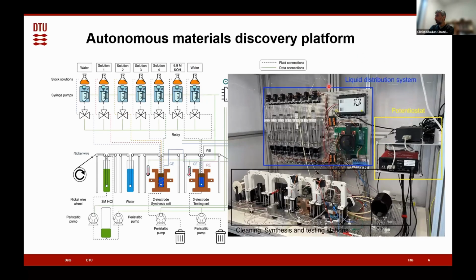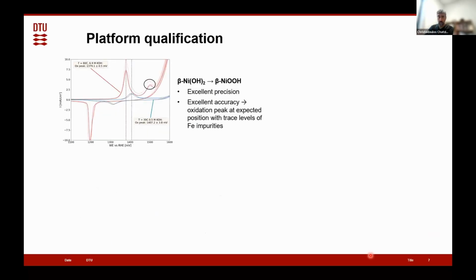This is the liquid distribution system, the potentiostat here, and this is the roll-to-roll testing station with the different stages and the collecting drum where the synthesized or tested catalyst is collected and can be traced back if further characterization is required at the end of the experiment.